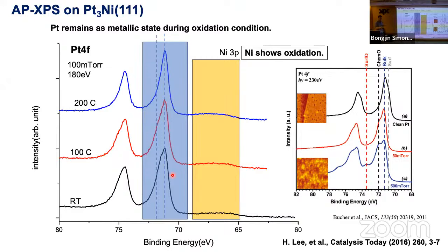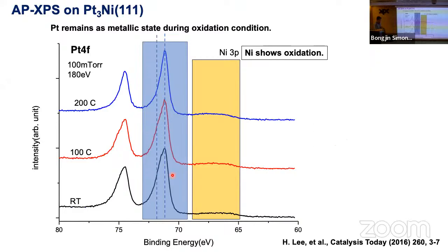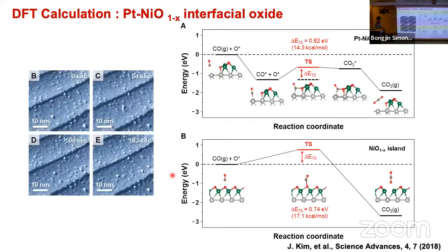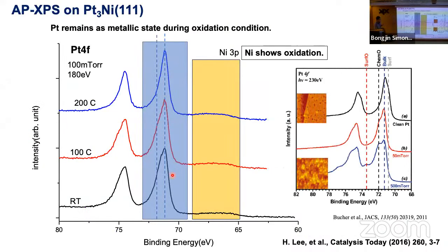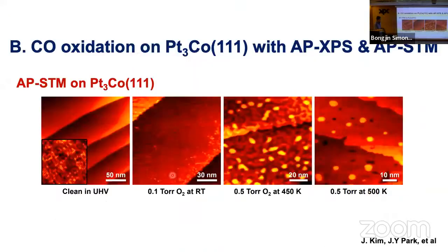In other words, even though there are similar structures like this and like that, the chemical state is actually different. And that was really the thing that we couldn't quite understand, because we thought we should see something like this, but nickel is actually not. So at the time, that was our homework. And then we got encouraged by this.